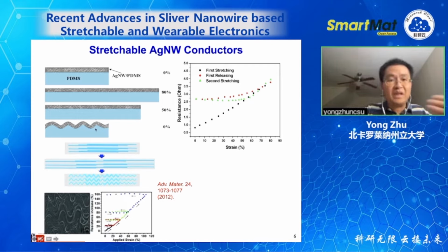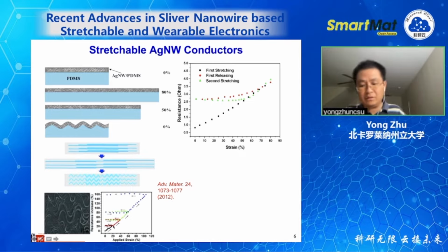This mechanism we have actually observed. Here, because it's embedded, it's hard to see, but we observed this in the case of carbon nanotubes in earlier work. We have carbon nanotubes on the substrate. We stretch them and see the sliding between the nanotubes, and when we release them, the nanotubes don't go back straight. Instead, they also buckle, in a slightly different way. This is buckling in plane, but otherwise the mechanism is very similar. And the resistance versus strain behavior is also very similar. When you release, it nearly goes constant.